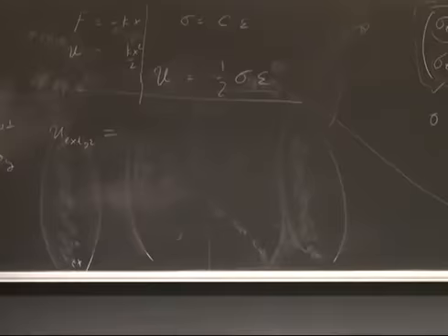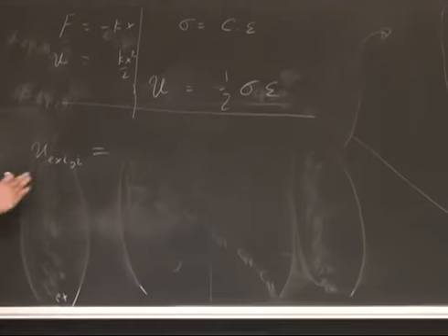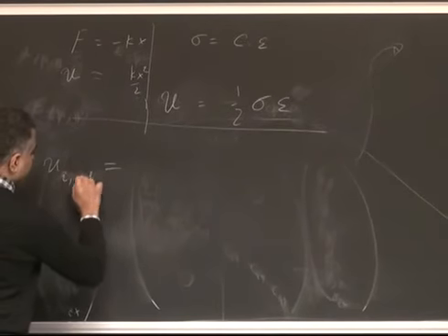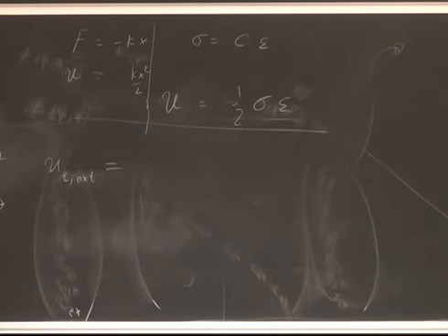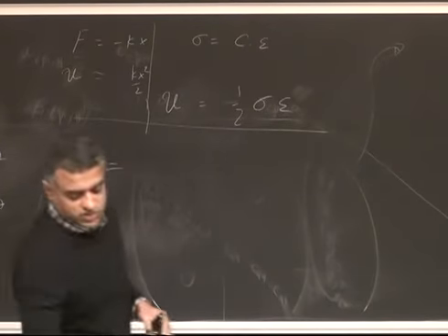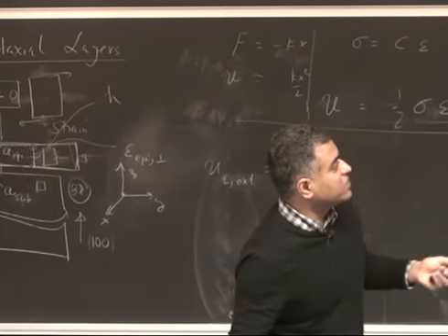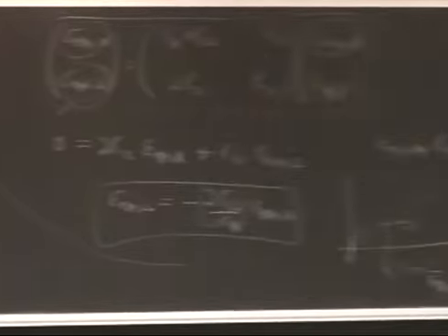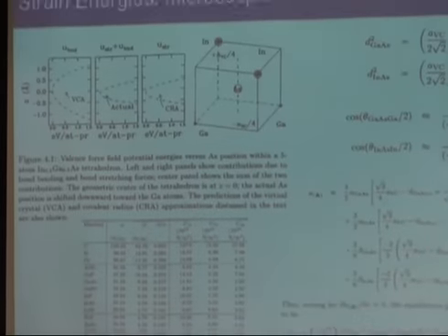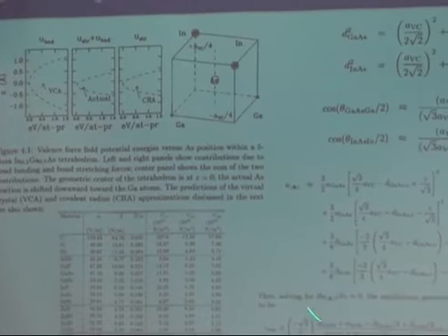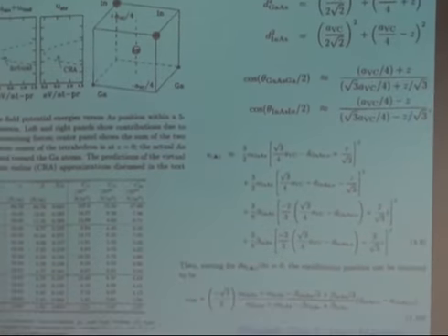Let me explain what these mean, right? Or U I external. So the strain is being applied here in this layer due to external circumstances, meaning this layer, because I'm trying to grow it on this layer and it's trying to conform, the strain is because of that. It's not internal. Remember, there is also microscopic internal strains. Microscopic internal strains are something we talked about in the last class, which is saying that, well, if you grow indium gallium arsenide, let's say it's a 50% alloy, but then some parts are 30%, some parts are 70%, let's say. And then the tetrahedra are strained. This is what we calculated in the last one. Those are microscopic strains, right?